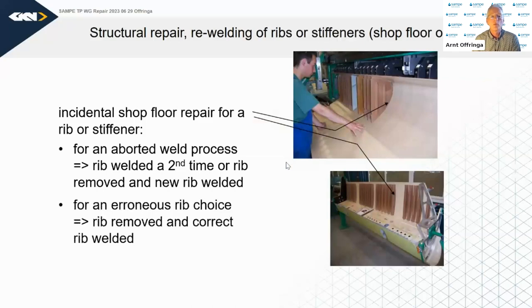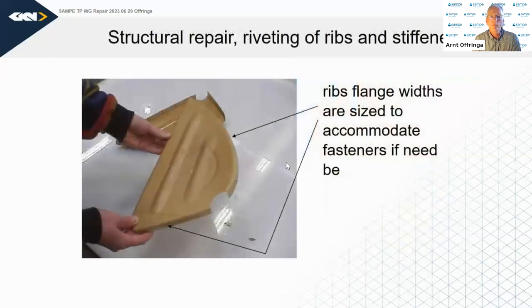What was done is to put a new rib at the same position and basically restart the welding process. And because it's a thermoplastic, you can basically do a process several times, two, three or even four times, without running out of process time. The rib flanges on this wing leading edge are sized not so much for the welding performance, which would require only a few millimeters of width, but a little bit bigger, like 18 millimeters, so they can accommodate a mechanical fastener, a rivet or a bolt, if necessary to repair. So the designers had in mind that this product should be repairable with conventional methods if necessary.